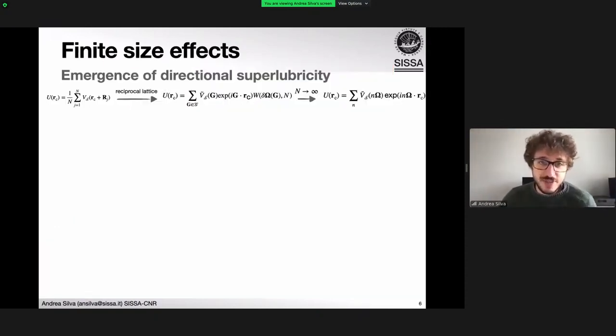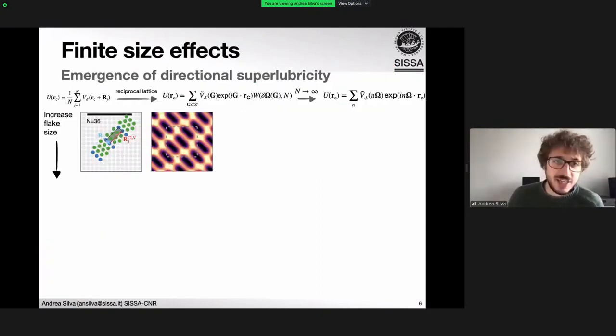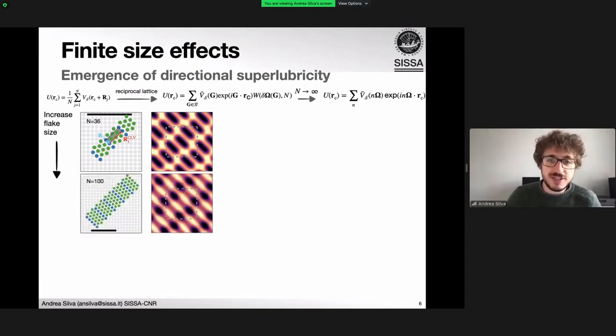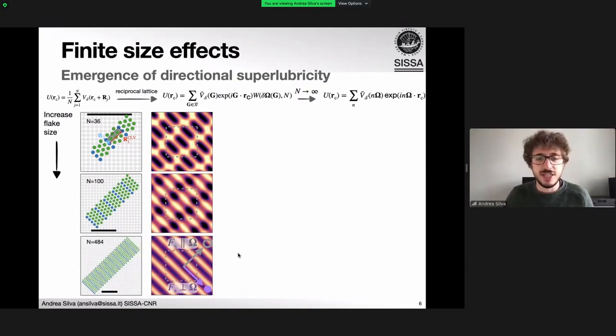We can play the same game with the new directional superlubricity we discovered. By increasing the size, we go from a clearly directional lock, with jumping between the minima of the potential, which are the black spots, to developing friction anisotropy, and in the end we have this true valley energy landscape.